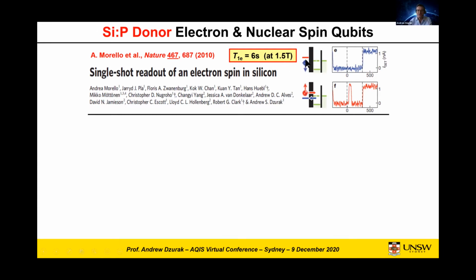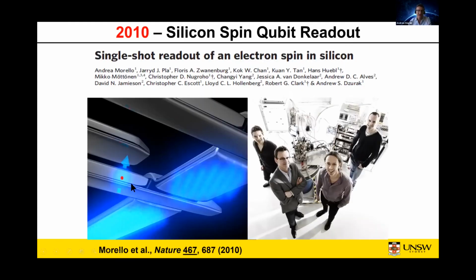Next to the single atom, if I go back to the cartoon over here on the previous slide, in this device, the atom was implanted into the silicon. And you can see this grey metal structure. This is aluminium electrodes that are fabricated using nanolithography, in this case electron beam lithography, on the surface of the silicon chip. And this blue region represents a number of electrons that are confined underneath this gate electrode, and this forms the island of a so-called single electron transistor device. And this single electron transistor device allows one to pass a macroscopic current that can be monitored outside the chip.